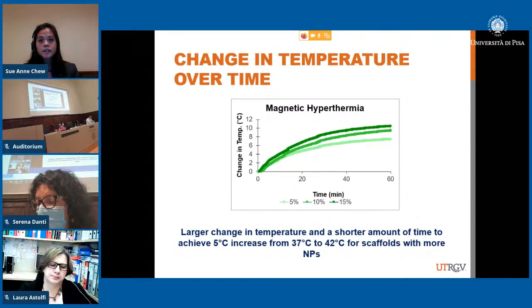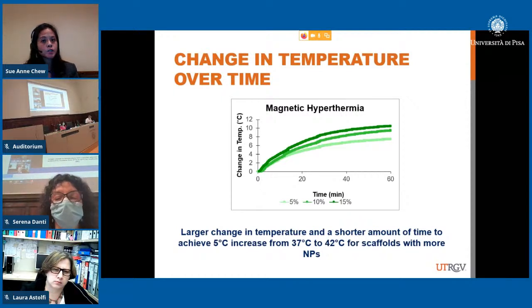So the first thing we looked at is how changing the amount of iron oxide nanoparticle changes temperature over time, right? Remember when we have the iron oxide nanoparticle and we provide that magnetic field, we can heat up the scaffold, or the surrounding area. So we saw that when we increase the amount of iron oxide nanoparticle, we were able to generate more heat, and we were able to increase the temperature, where we were targeting a change from 37 degrees Celsius, which is physiological temperature, to 42 degrees Celsius.